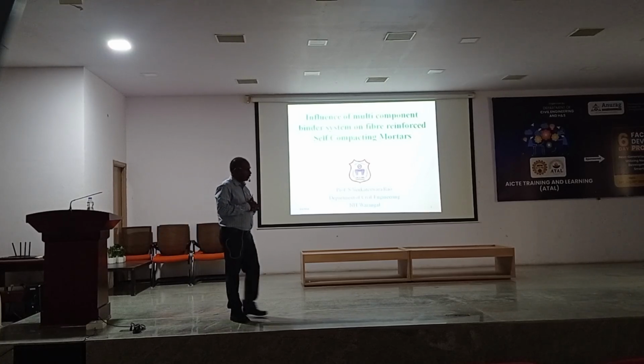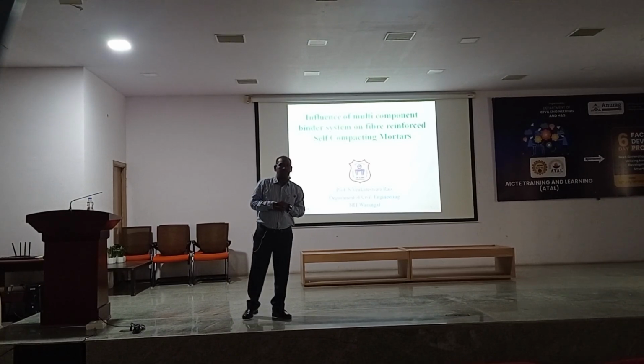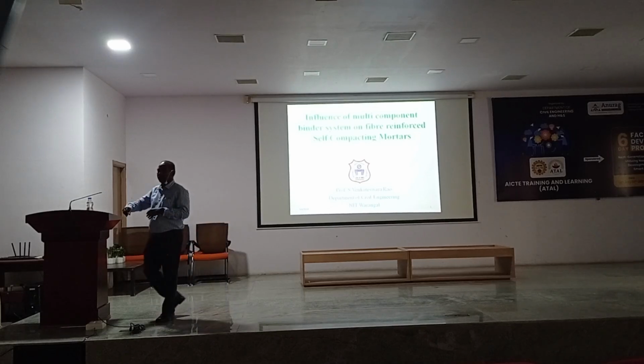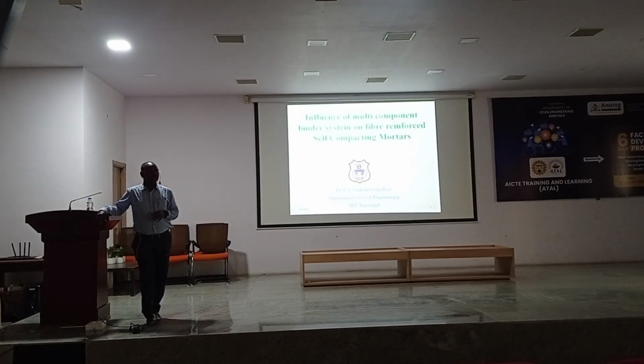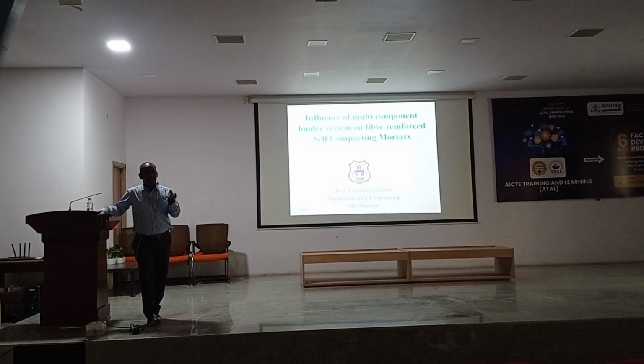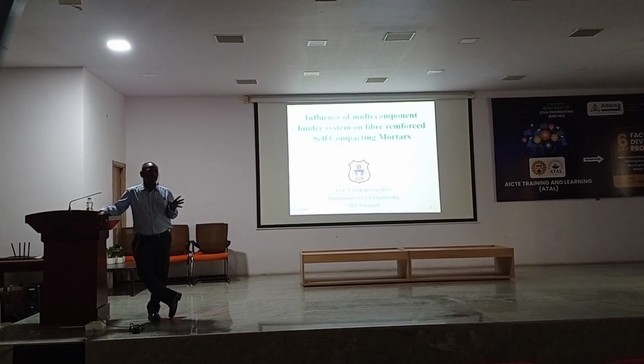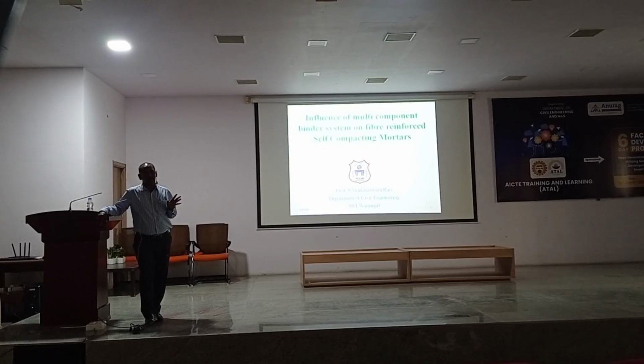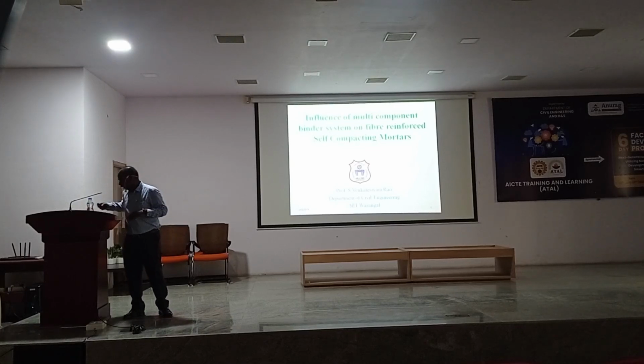One more major difficulty in geopolymer concrete is fast setting. If you cast that concrete during midday, that means 12 noon to 2 p.m., without taking the material from that drum or mixer, it will settle, it will harden. My students face a lot of problems. Without casting, the entire concrete is hardened and thrown away. That's why you can use a little bit of cement and replace the cement with other materials. Whatever industrial byproducts are available, you can use. That is nothing but multi-component binders.